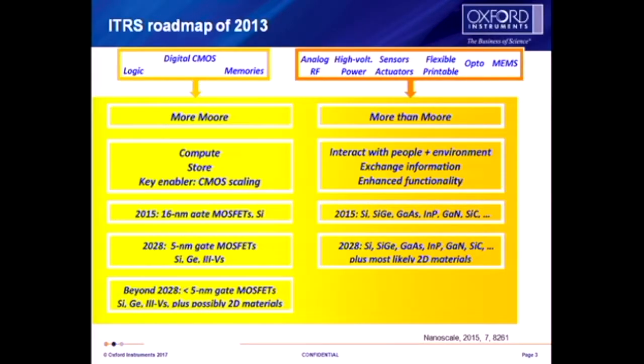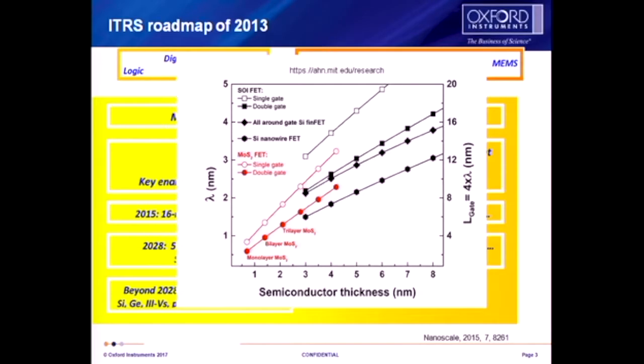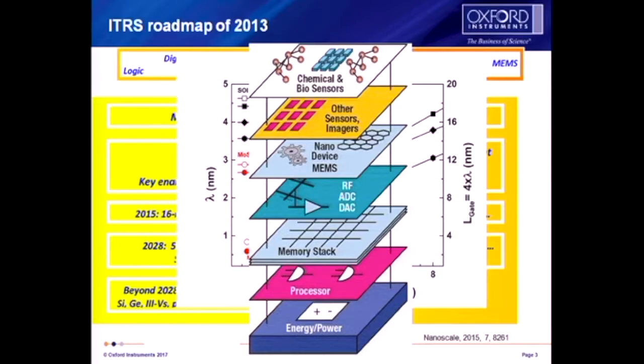So why the interest in these 2D materials? Well, if you look at the ITRS roadmap, which I don't think exists anymore unless it's ITRS 2.0, you can see that slowly but surely we'll be coming down in thickness of materials and gate lengths, and these all have an effect on the material properties and could affect the actual mobility inside the films. With 2D materials, where you've got van der Waals structures, you're actually getting less of this mobility loss. So it's very key in the roadmap towards achieving 7 nanometers and beyond. But there are other useful film properties as well.